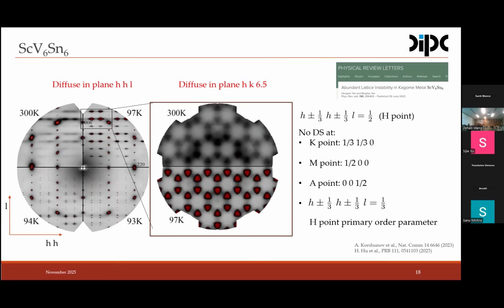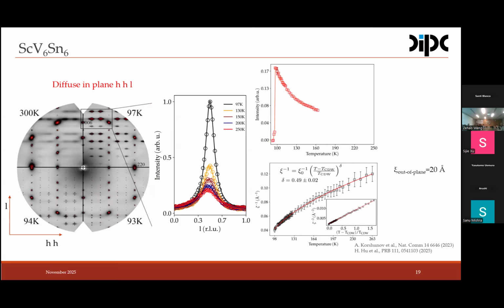this ScV6Sn6. So we can actually parse in detail the diffuse signal. We make cuts along the Z direction and fit it to a Lorentzian line. We see how the intensity increases and sharply drops. And most importantly, the out-of-plane correlation length follows an order parameter with a critical exponent close to 0.5 along the Z-axis, which essentially tells us that the phase transition might be mean field-like, right?